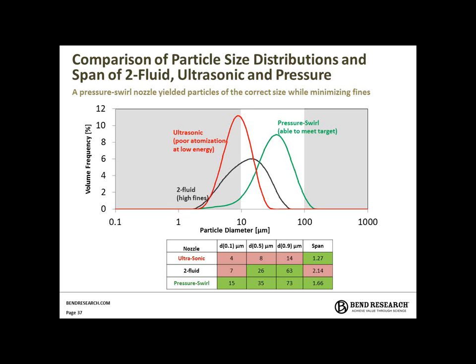Similarly, the two-fluid nozzle, though very, very highly tunable, typically naturally produces a lot of fines, seen by that kind of tail on the sub-10 micron range. Whereas with the pressure swirl atomizer, we were able to meet all of the particle size needs as well as the span requirements for the right delivery particle size distribution.